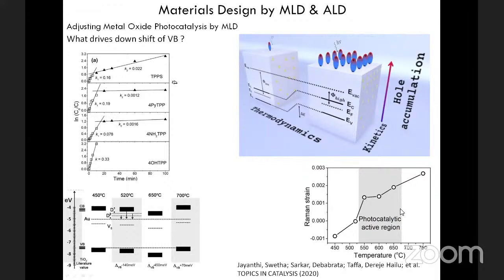The strain induced or generated in the oxide when annealed at this elevated temperature and cooled down results in a shift of the valence band and conduction band, and this is what you can see here. So there is a downshift that is marked here, and this is the downshift that we found. This downshift affects the thermodynamics of the system, because now when you photogenerate holes, these holes are much deeper with respect to the vacuum level, which means much more oxidative. So they can break up molecules that are very stable and usually cannot be broken up using such an oxide.